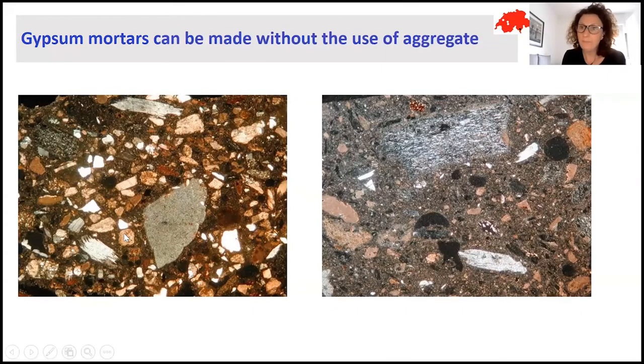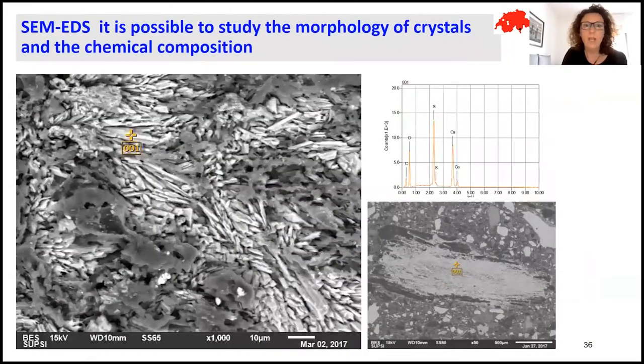As I said before, gypsum mortars are particular because they can be used with the addition of aggregate, but also without the addition of aggregate, as we see in the right image. Because of this increasing volume of gypsum, there is not always a need to use aggregate, and in some cases it can also be used for producing, for example, very fine plastering inside. By using the scanning electron microscope, it's also possible to study the gypsum residues, to better see and study the morphology of gypsum crystals, and also to have information about the elemental composition.